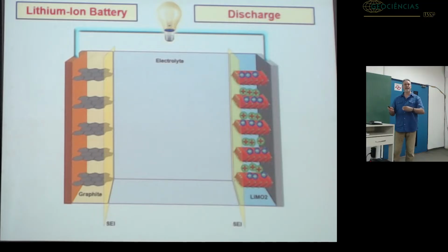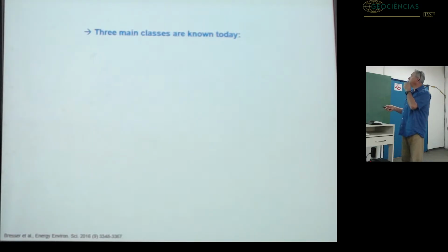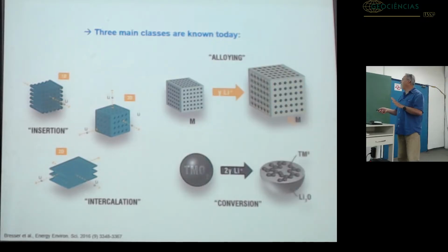Just the lithium site gets vacant, and the iron in the octahedron oxidizes from 2+ to 3+. So it is a reversible transition, and lithium can go out and in response to charge and discharge of the lithium-ion battery. A very short introduction to lithium-ion batteries.